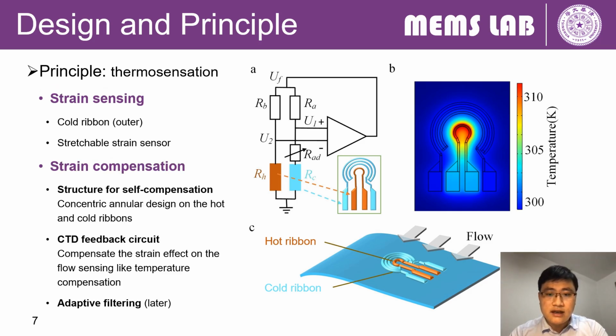It is noticed that the resistance of the two ribbons may vary with the mechanical strain. Fortunately, the concentric annular design of the two ribbons helps to make a self-compensation to strain effect. Specifically, the cold ribbon also serves as a strain sensor that compensates the strain effect on flow sensing using the hot ribbon, just like the temperature compensation. Taken together, the stretchable sensor using the hot and cold ribbons competently detects flow, temperature, and strain simultaneously.